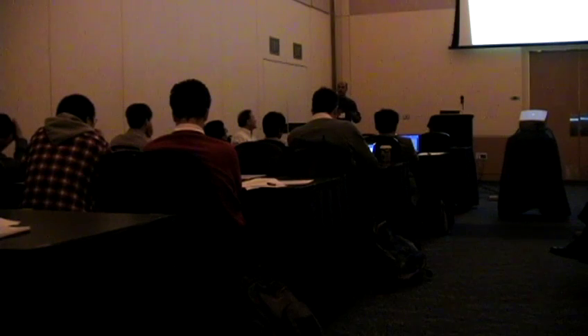Yeah, that's fantastic, but what I'm trying to say is that it's probably not worth the effort, depending on what you want to look at. This system seems to be very well screened, so the Poisson equation is not that important, and the two components are pretty much independent. On the pulse, what happens is you have the oxygen migration, and then in the bias regime, all the oxygen stays put, and then you have just a pure electronic conductivity that changes from position to position depending on the concentration of the vacancies.